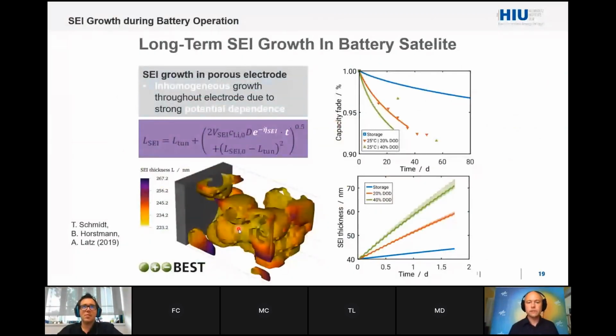the electrode. So we implemented this model in our microstructural simulation, and what we found, in cooperation with JAXA, the Japanese aerospace agency, who had a battery in space for 15 years in the Reimei satellite, and we investigated their data. What we found is that if we simulated the SEI growth during different depths of discharge and at storage, we find a huge inhomogeneity of the SEI thickness across the electrode, which we did already in 2018, in the PhD thesis of Tobias Schmidt. There are huge differences in the thickness in the range of several nanometers, sometimes tens of nanometers.